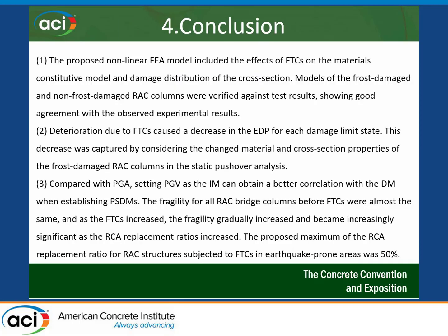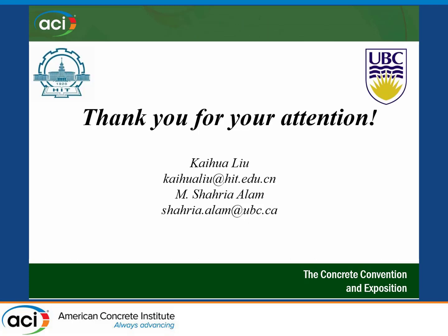In conclusion, the proposed nonlinear finite element model developed in OpenSees was effective in accurately calculating the structural capacity, with very good agreement between experimental and analytical results. PGV was found to be a better intensity measure for recycled aggregate concrete bridge piers due to its good correlation with the damage parameter. The recommended maximum RCA replacement level is 50% for bridge columns in earthquake-prone areas.